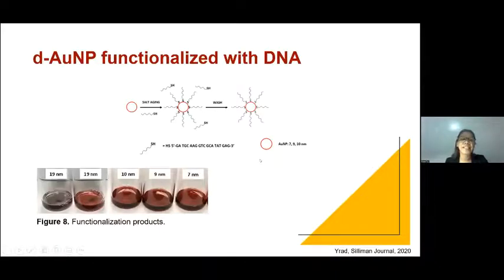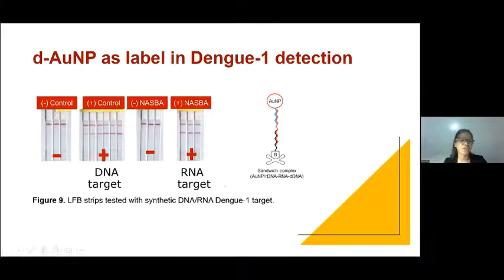The different sizes of gold nanoparticles were functionalized with thiolated DNA, and figure 8 demonstrates that 10 nanometer, 9 nanometer, and 7 nanometer D gold nanoparticles produce stable functionalized product. We were not able to functionalize, however, the 19 nanometer gold nanoparticle under the same conditions of the functionalization reaction.